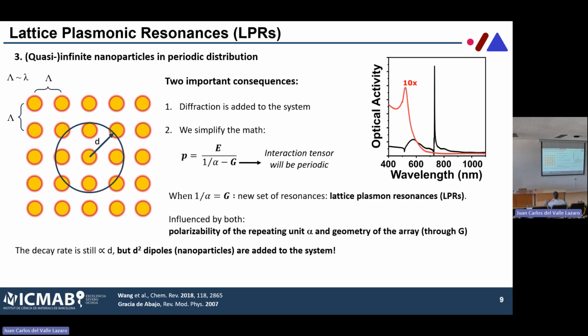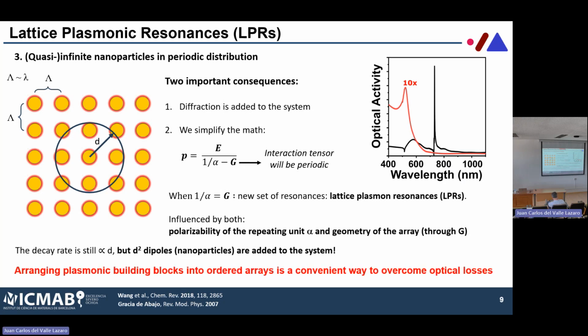And so basically at the end of the day, what this is telling you is that all the localized plasmons of the particles interact with each other in phase in certain conditions, the one described by the denominator there. And this basically ends up with having plasmons that are delocalized. So you can imagine it as the entire array oscillating in phase. Consequently, you have long-lived plasmons that have very sharp features. So basically, the take-home message here from these little introductions is that if we manage to arrange plasmonic building blocks into an array, it should be a very convenient way to overcome the optical losses of the system.